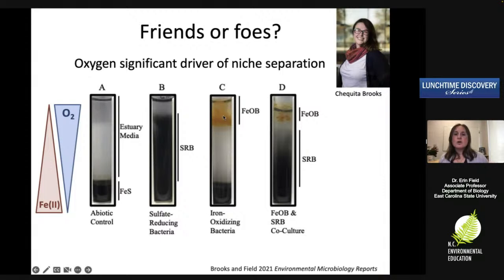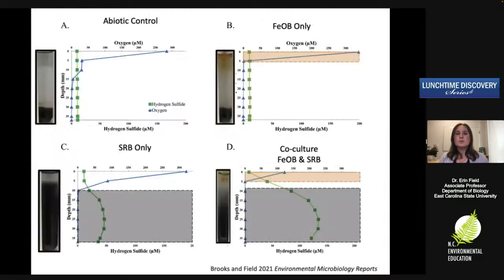The iron oxidizers will grow right until about oxygen disappears. So we expect this separation. And that's exactly what we see when we grow them together. The iron oxidizers want the oxygen, sulfate reducers don't. But we notice there's a clearing space in between the two. And so we did this study over a few times.